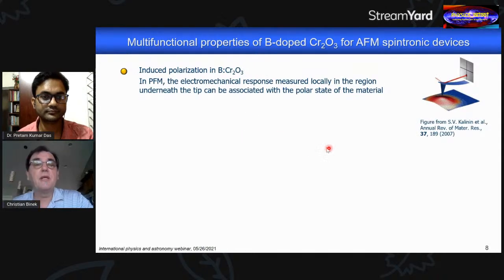And we confirmed that and measured that by a method that is called piezo force microscopy. So that is very well known from the investigation of ferroelectric materials. If you have ferroelectric order locally, then this ferroelectric order is always accompanied by a piezoelectric effect, meaning a local deformation of the material. And by measuring that deformation basically with an atomic force microscope, you can conclude that below was some polarization, and that allows you then basically to be sensitive to polarization.